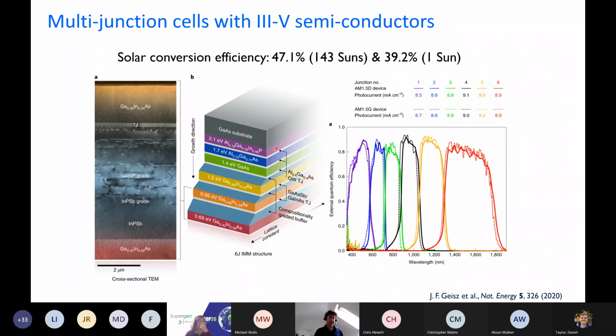But the problem is these III-V semiconductors have to be almost perfect crystalline thin films to work. And to do that, they have to be grown very slowly. So there is a significant amount of effort on improving the growth and trying to make cheaper production methods for these III-V semiconductors to make these multi-junction stacks less expensive, but they're still many orders of magnitude away from being suitable for terrestrial PV.